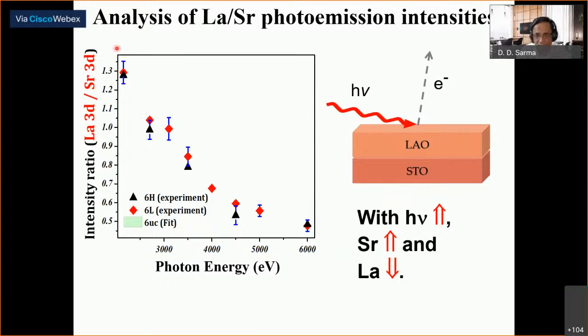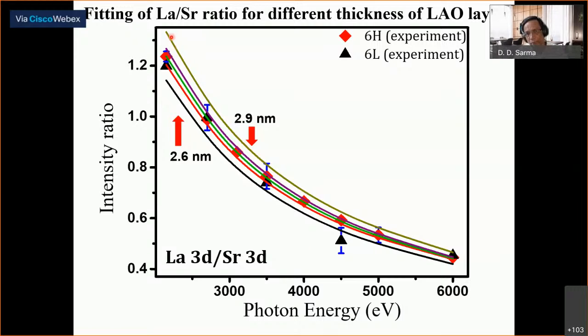It turns out that this intensity variation, besides the fact qualitatively seeing that it is going down and so lanthanum is on top and strontium below, I can model it and find out what is the expected intensity ratio variation as a function of photon energy if I had 6 monolayers of lanthanum aluminate on top as this sample is. This number 6 represents that by my design, I wanted to make 6 LAO layers on top of STO. And then I can calculate for different thicknesses of lanthanum aluminate what the expected theoretical ratio should be, and that I show over here.